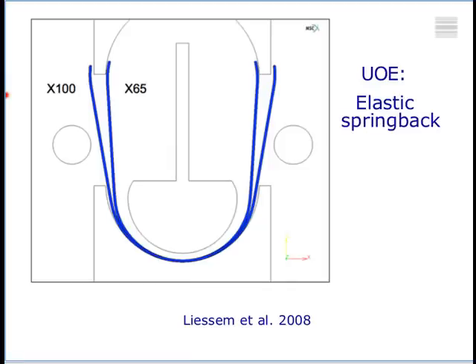So X65 is the conventional line pipe steel, which starts off as a flat piece of plate and then it is bent into a U-shape. That U-shape is then turned into a circle, welded together, and expanded to make a perfect circle. This is the sort of die that you use for making the U operation, bending the plate into a U-shape. If you use a stronger steel, then when it comes out of the die, it will spring back. That means the shape will no longer be this perfect U, but it will change to this as soon as it comes out of the die.